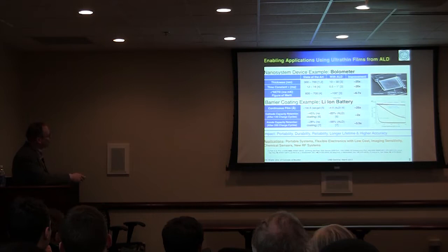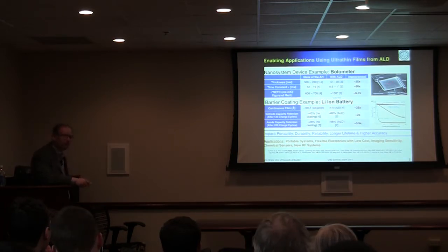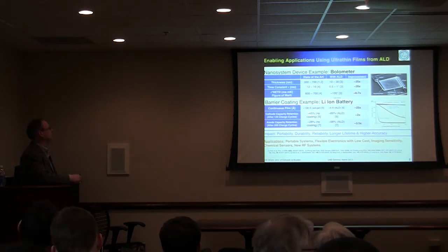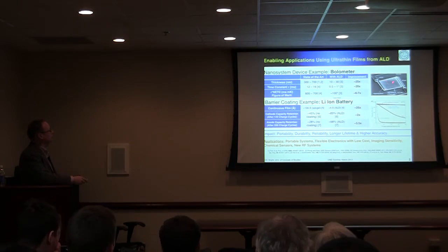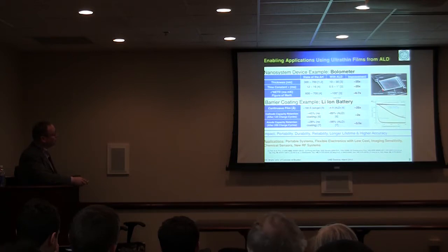Another more recent example of ALD for a standalone micro and nanosystem, or more a nanosystem, is the ALD-based bolometer. This one is out of Tom Kenny's group at Stanford, and we do collaborate with that group. So I'm going to mention a few more things about this project. What you're seeing here is a suspended plate, or suspended membrane, made out of platinum ALD. The reason you want to go to ALD here is you want the thermal time constant to go way down for the bolometer performance, so you want an ultra-thin film. And here the platinum itself is used as both the detector and the temperature-sensitive resistor.